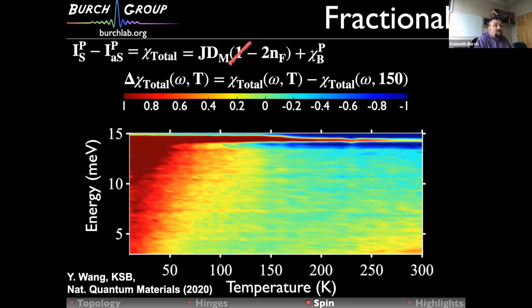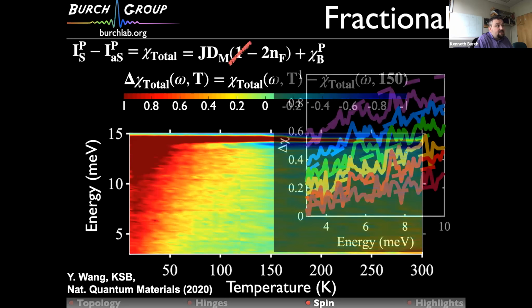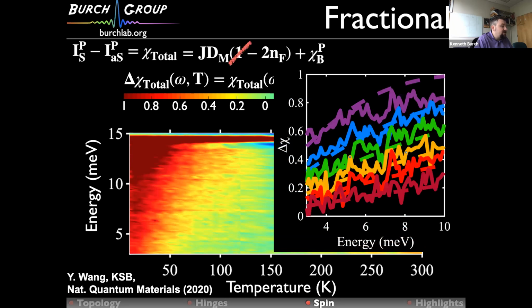And so to prove that they're really fermionic, we basically take the response at the lowest temperature, we multiply it by the appropriate Fermi function, and then we took cuts at different temperatures, and that's here. So the solid lines are the actual data, and the dashed lines are not fits, but just the predictions of what should happen with Fermi functions. And so we find that the temperature and energy dependence of this continuum is completely described by Fermi statistics, and therefore is consistent with these fractional excitations.